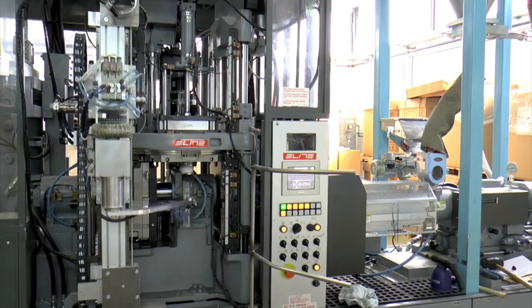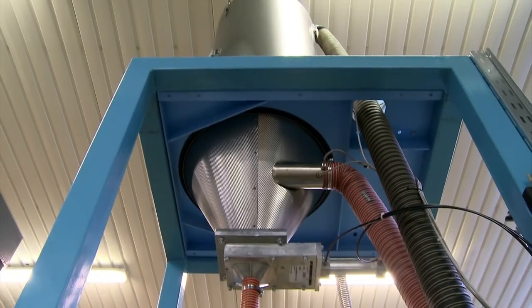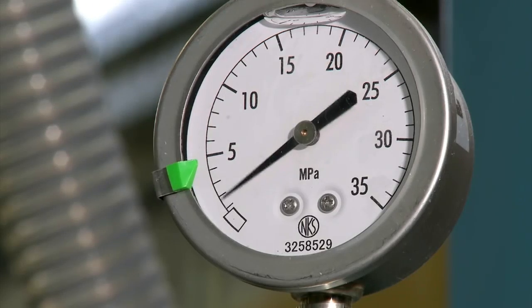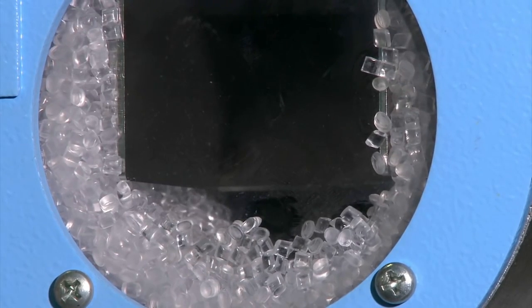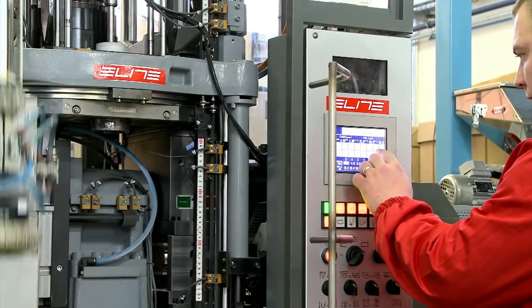Bottles are made of Tritan, a new bisphenol-free, shatterproof transparent polyester that has replaced polycarbonate, using injection stretch blow molding technology. To have a perfect Tritan bottle, the material, due to its high hygroscopicity, must be first warmed and dried. Only then is the material loaded into the extruder to fill the mold and create the so-called preform.